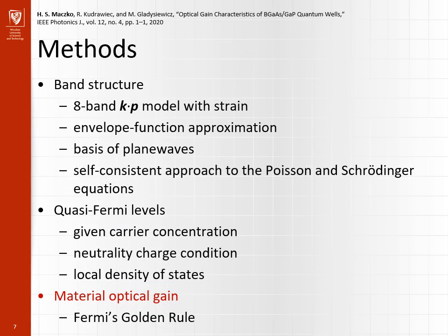First of all, electronic band structures of quantum wells are computed based on 8-band k·p model with envelope-function approximation. Envelopes are expanded into the basis of plane wave functions. Since barriers of the system are made of indirect gap material and the thin film can be barely direct gap material, a self-consistent approach to the Poisson and Schrödinger equations is crucial and applied.